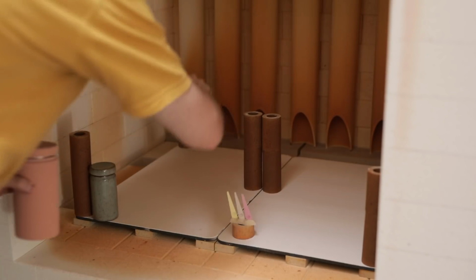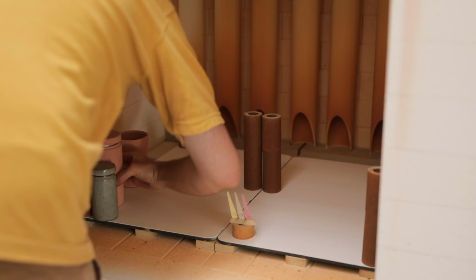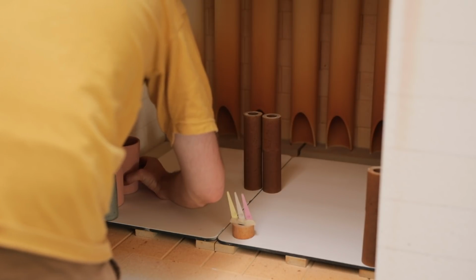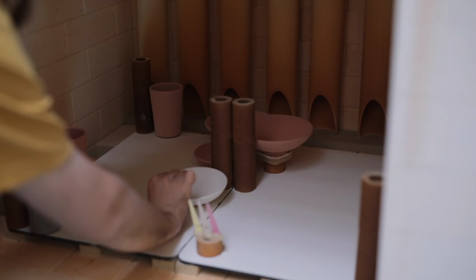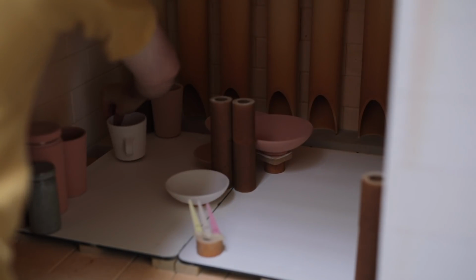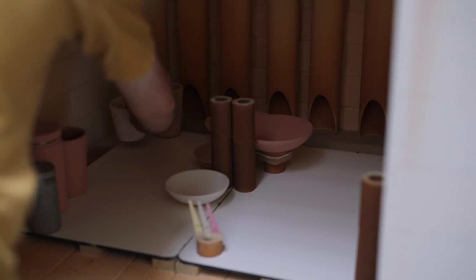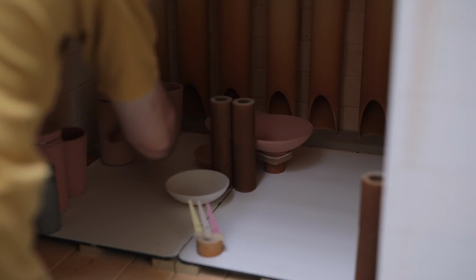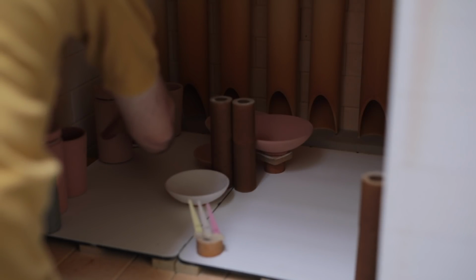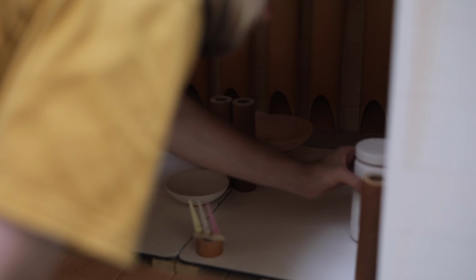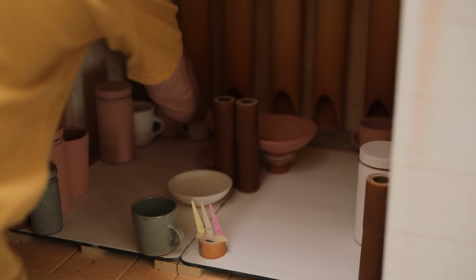Now it's time to pack the kiln, loading the pots onto these pristine new kiln shelves that are ever so thin. The cone pack may look like it's placed randomly, but in actuality it's opposite where the spy hole is in the kiln's door, and it's crucial to position it correctly, as I need to be able to see these during the firing. As for placing the pots in, the general rule is that none of them can touch each other, so in between each is about 2 to 3 millimeters.